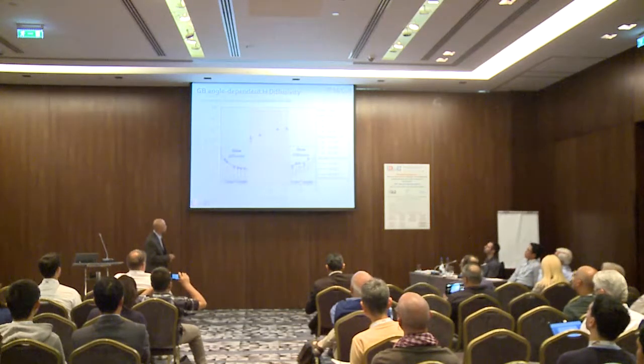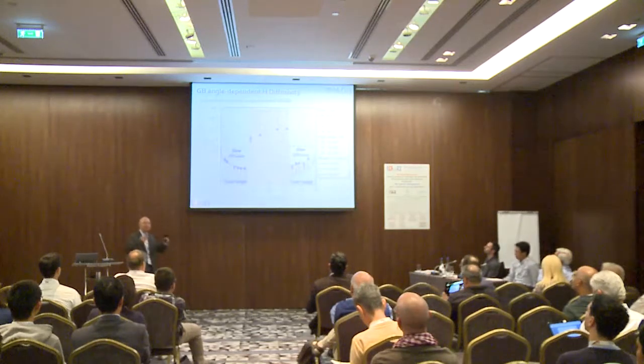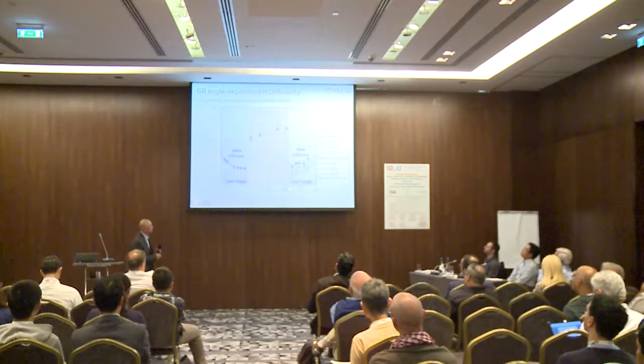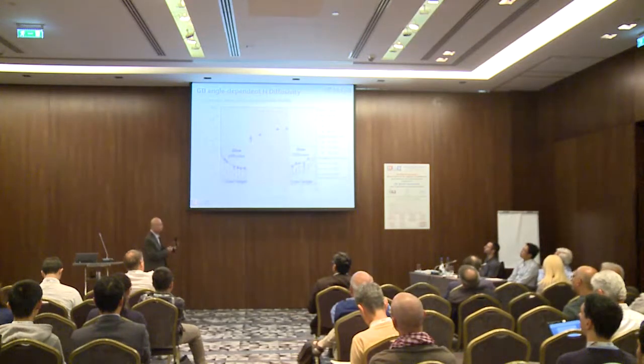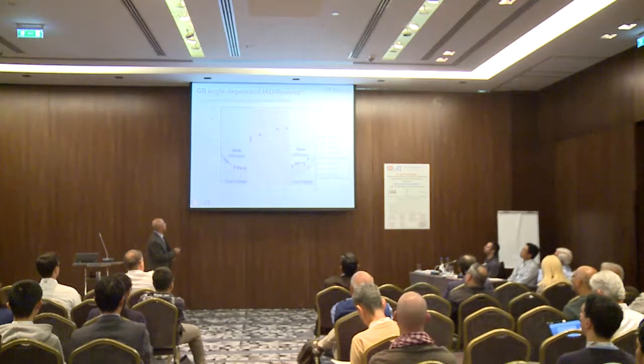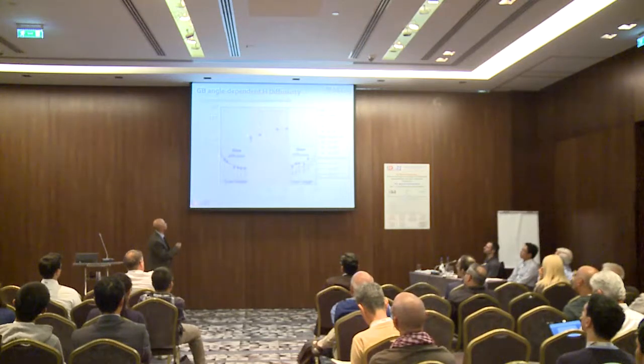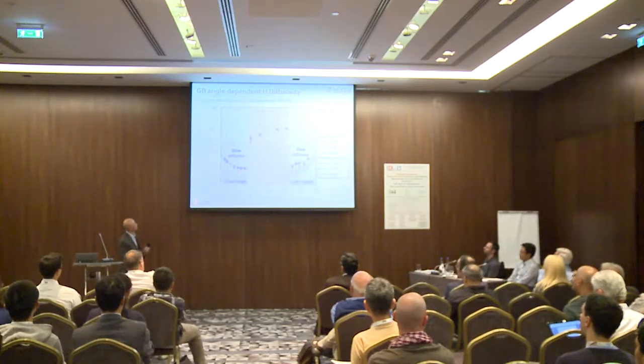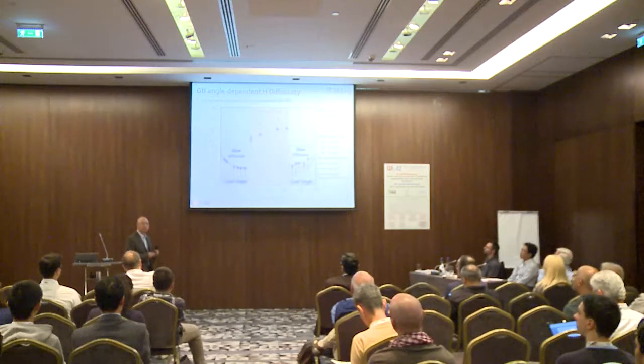And interestingly, if you look at the tilt angle, these two regions are actually low angle, although it's not a typical kind of low angle grain boundary, because a typical low angle would be much smaller than this. And you may wonder, if you're not really familiar with grain boundaries, why this is low angle? It's because of symmetry. Okay, so because of symmetry, this region is also a low angle grain boundary regime, while the middle is high angle. So that makes us wonder, why is there such a drastic transition from low angle to high angle, where the diffusivity suddenly jumps from this value to here? Okay, so this makes us think, what happens?